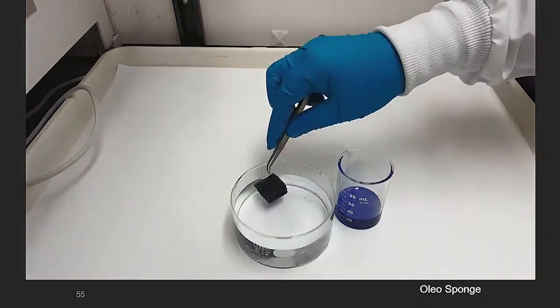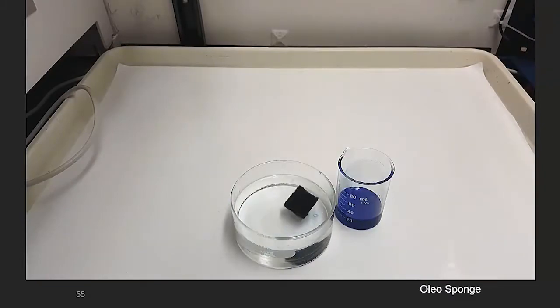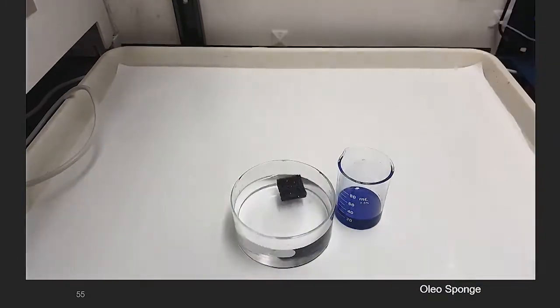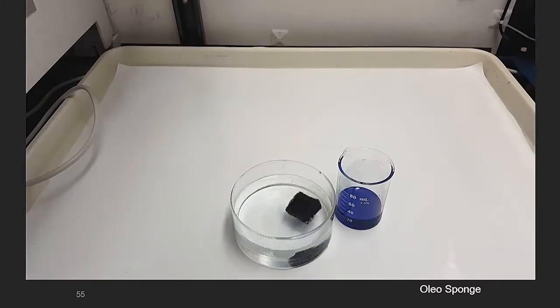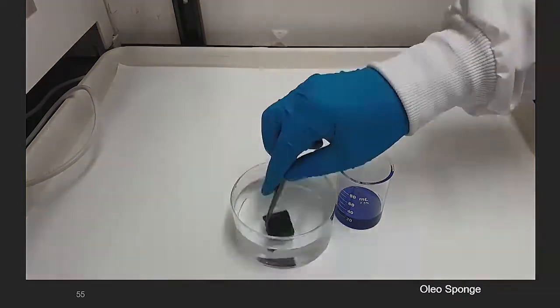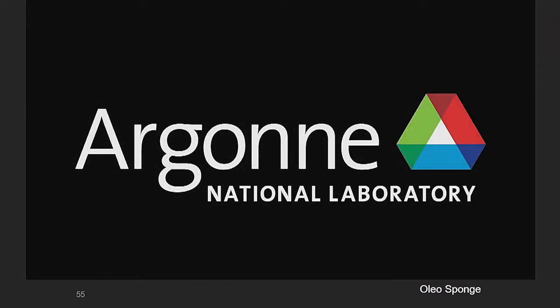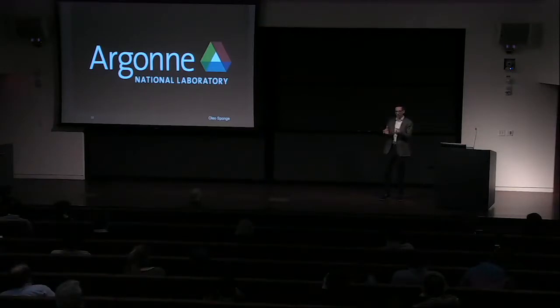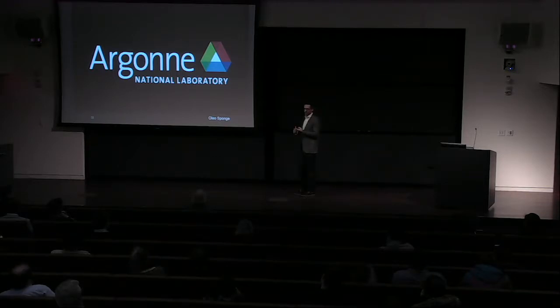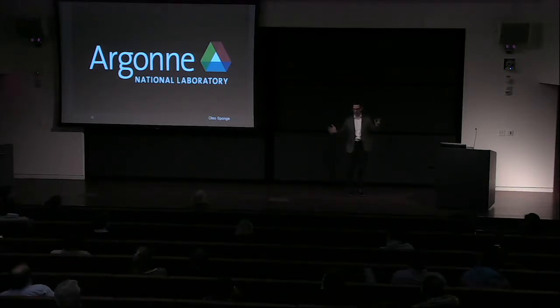I haven't counted. I actually don't know how many cycles there are in this particular video, but we have yet to find a point at which the performance degrades. So I think we've done it 20 or 30 times in a cycle with no drop in performance. I don't know what the limit is. Presumably there is some point at which it wouldn't work anymore, but it's a lot of cycles. So we were excited when we got to that level, but of course we're talking about cleaning up oil spills that are bigger than a little puddle in a crystallization dish in the lab. And so we needed to scale this up. And what I'll show you next is that same demonstration done at a scale that is now this large instead of this large.